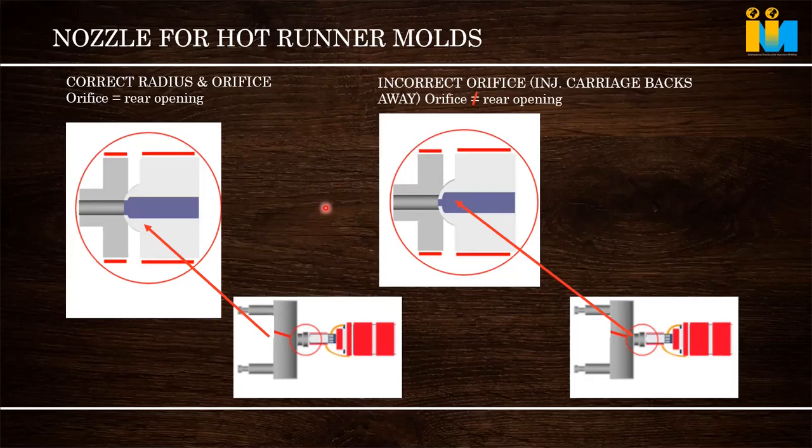But in the case of hot runner, it is not like that. In the case of hot runner, if you are keeping the machine nozzle diameter smaller than the entry of the hot runner screw bush, what happens? There will be a hang up area here, due to the same effect. So this area will burn off and go to the part. This is the biggest problem. Many people, when Prasanji comes and recommends keeping the same diameter, with a very small difference, all the molders tell us no, we are using the same nozzle for all the hot runner, cold runner, everything. We cannot change, that is a standard nozzle. Everybody tells this. Machine people have given this as a standard nozzle.